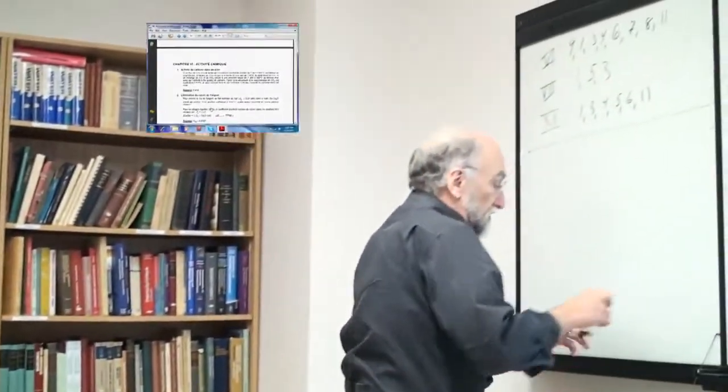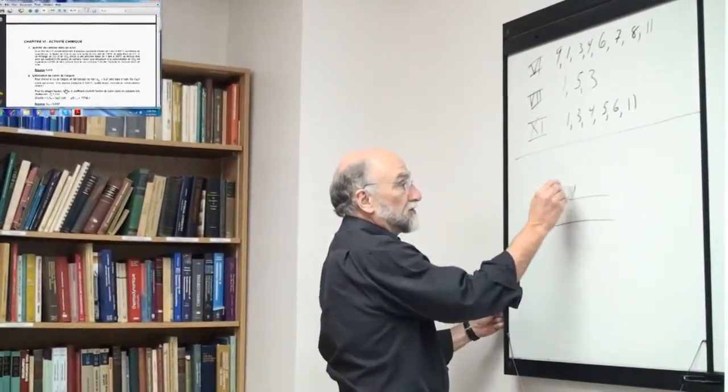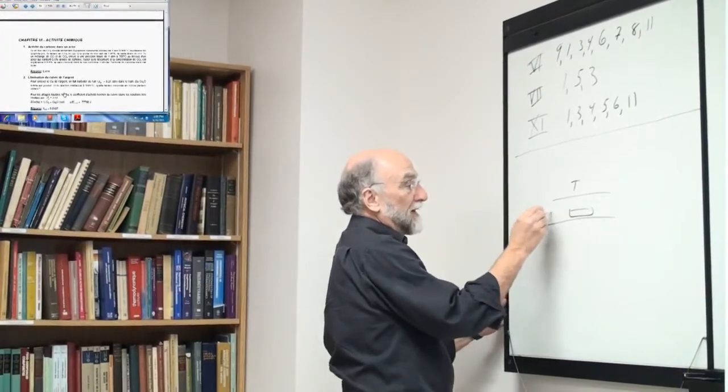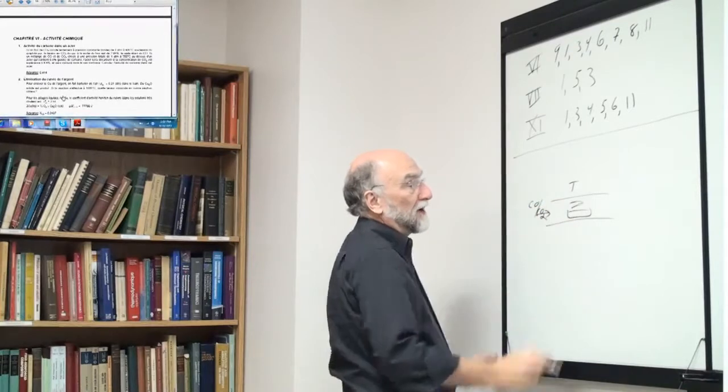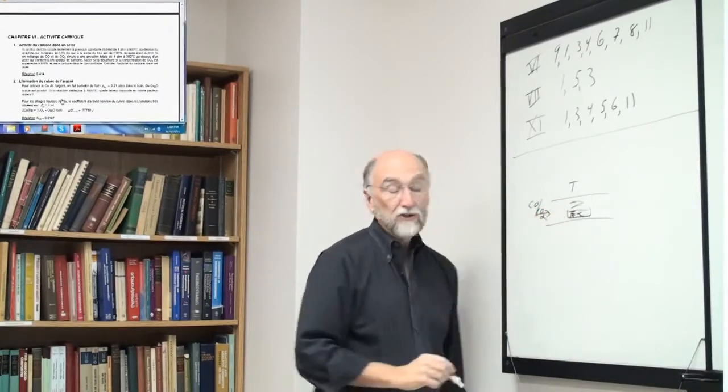Okay. If we want to look at number 1, go on over here. Number 1 was the activity of carbon in steel. This is kind of a classical method to measure the activity coefficient. You would take a boat in a furnace at some temperature T. You pass here a mixture of CO and CO2 in the gas space. Here you have your iron-carbon solution.